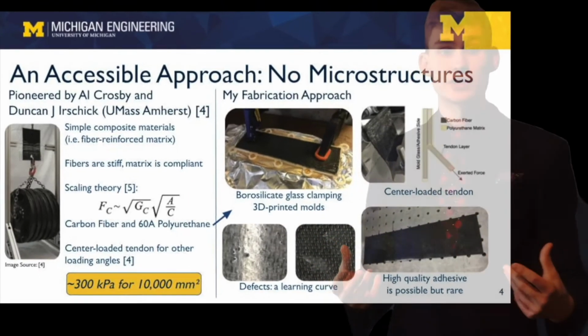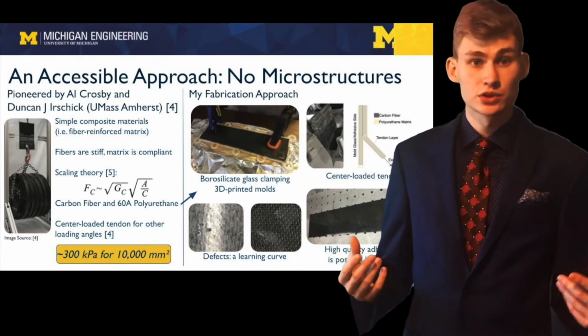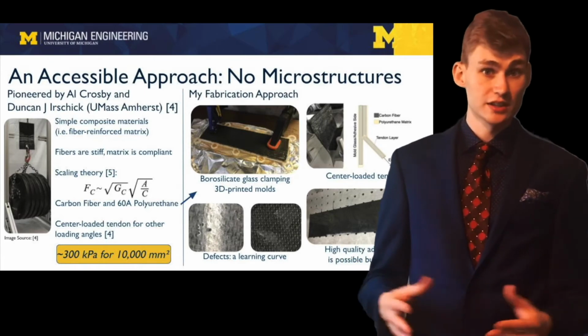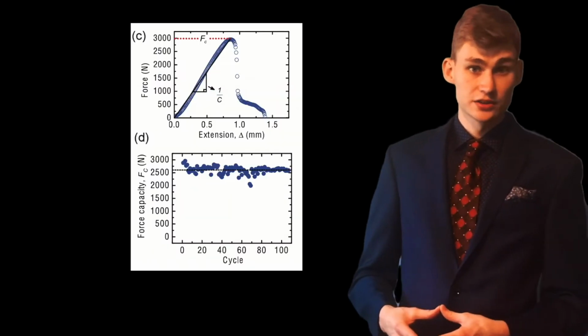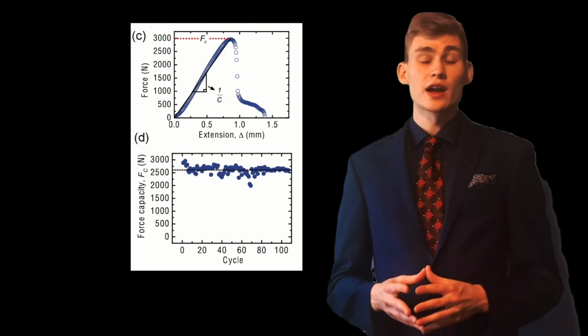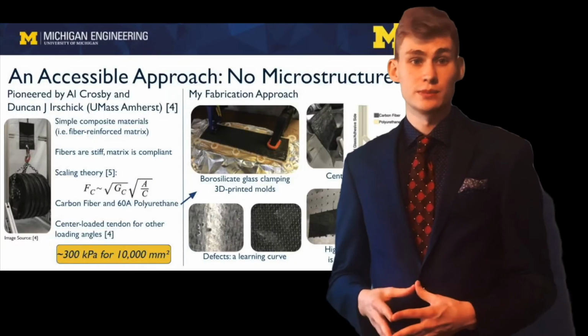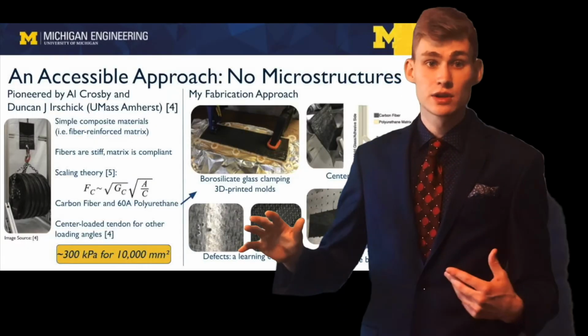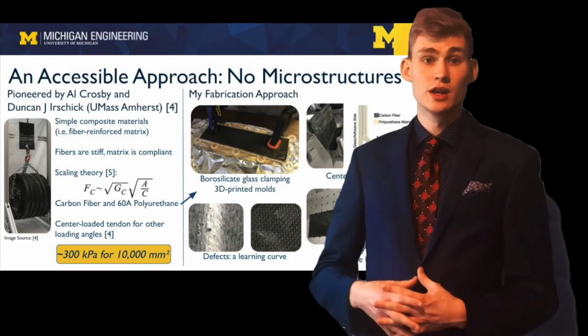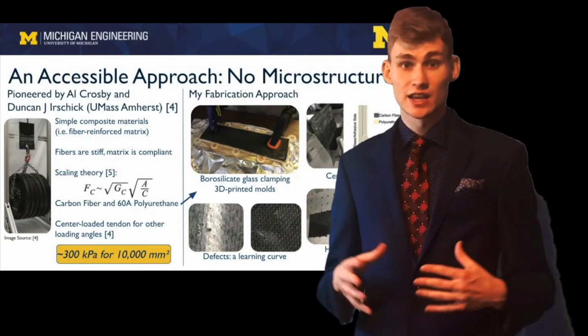I had high hopes for this approach, as research from UMass Amherst showed an unprecedented shear stress capacity of around 300 kilopascals for an adhesive pad with an area as high as 10,000 square millimeters. Better performance than any of the other approaches by a wide margin, demonstrating that this approach scales much more efficiently than all the others.